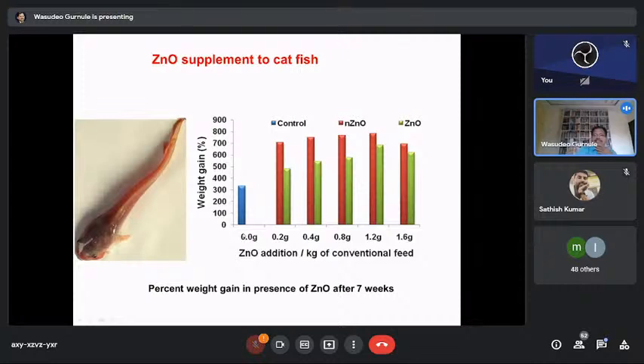There is an initial value, this is the control. Then after a few days, 0.2 gram increase, 0.4, then 0.8, 1.2, 1.6. So the estimate has been carried out over 7 weeks, and there is an enhancement in the weight of the catfish when we give food of this type to the catfish. After 7 weeks, it is observed that there is a much greater gain in the weight of the catfish when we use nano size zinc oxide.